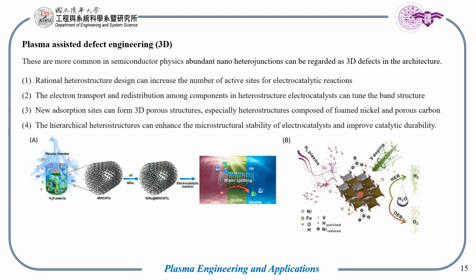In figure B, we can see vanadium doping combined with low temperature radio frequency plasma reduction to construct a heterostructure of vanadium doped NiFe or Fe LDH nanosheets, which is rich in oxygen and nitrogen vacancies, and these vacancies help in increasing the efficiency further.